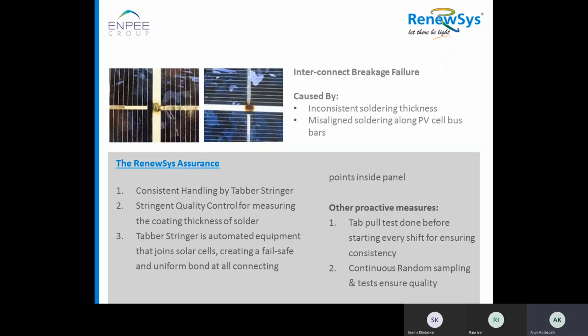Other pre-checks will be done at the start of every shift to ensure consistency. Before starting the shift, the first cell processed in the tabber stringer goes for a tab pull test. This tab pull test is nothing but checking the joint strength between the interconnecting copper and the solar cell. Once the machine is qualified, only then will the machine be released for regular production. If it doesn't pass, the machine will go for maintenance. In the same way, we also do continuous random sampling tests to ensure quality. We take some cells from the tabber stringer and do tab pull, because we know tab pull is one of the critical parameters in order to ensure that there are no field failures.